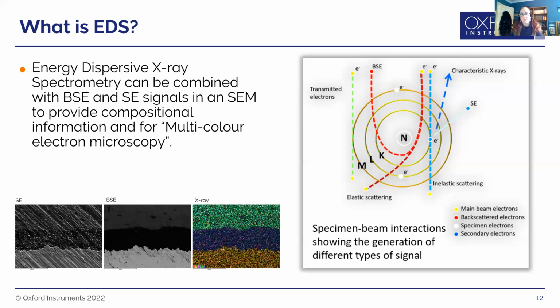And then what we can do is accumulate all these signals: the secondary electron signal, which gives you a lot of topographical information, and the backscattered electron signal, which, because it's due to the main beam electrons being deflected by the atomic nuclei, gives you more of a backscattered signal where you have a higher density material. And you can see that here we've very clearly got some density differences. And then we can introduce colour, which is the elemental composition of these areas. And this is a barrier between an implant material down here and bone in this example.